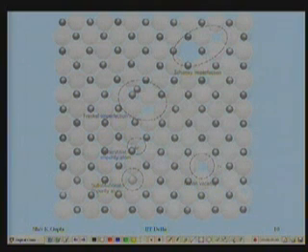One of the bivalent ions should be missing from its location so that it becomes electrically neutral. But then the material you have is no longer the formula FeO. It is Fe(1-x)O, with x less than 1, where x can be a very small fraction of 1. So that is possible, and that happens in ionic crystals. That happens in all these compounds of transition metals usually.